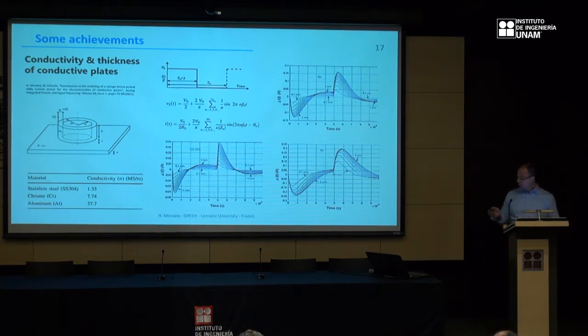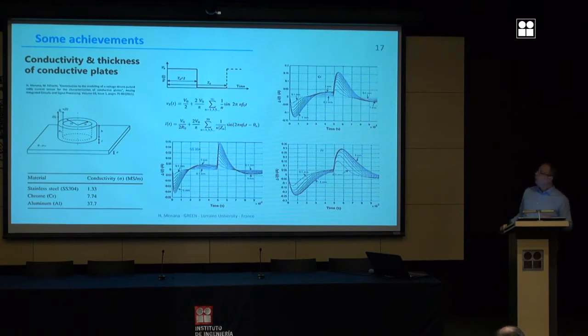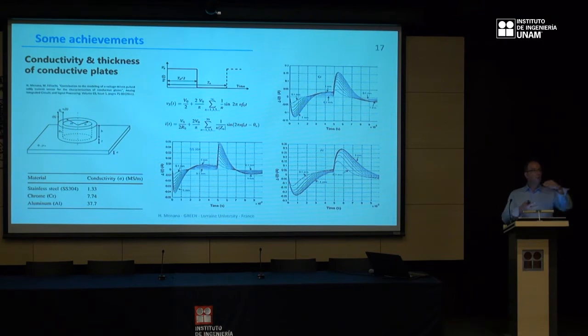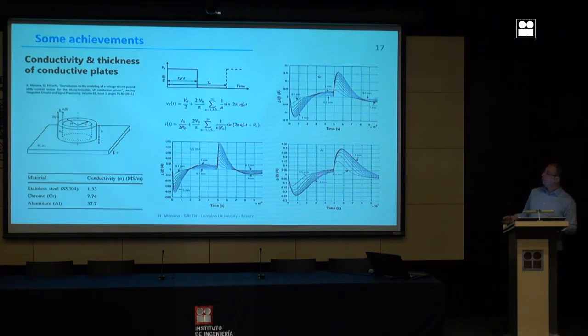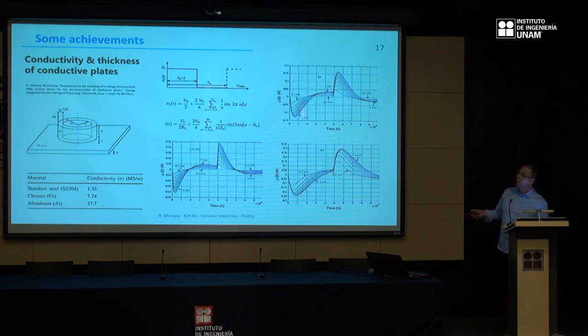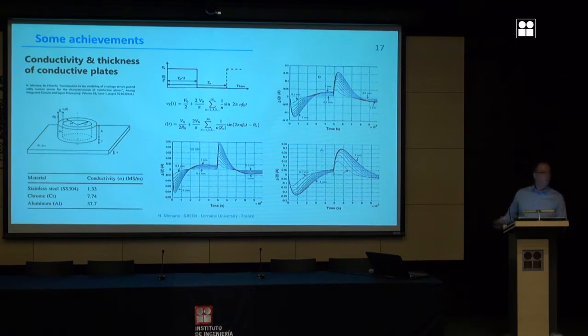In this work we have studied pulse eddy current testing to characterize thickness and conductivity of conductive plates. We considered different plates with different thickness and conductivities, and we used numerical modeling to model the system of a coil above this plate. We have noticed that the conductivity of the plate mainly affects the zero crossing time, and the thickness of the plate affects the magnitude, or the maximum, of the eddy current variation in the probe.